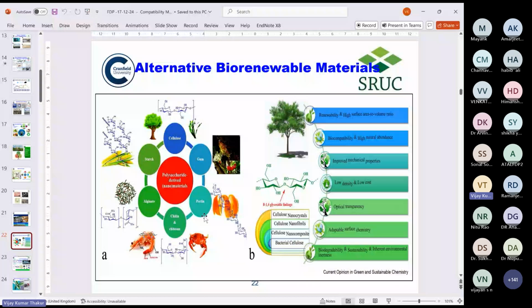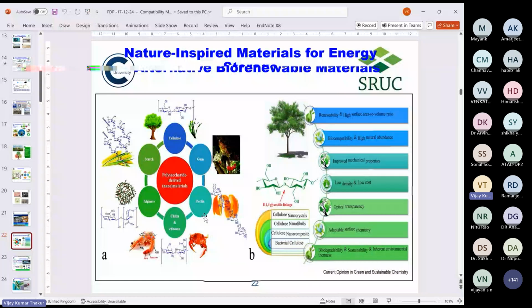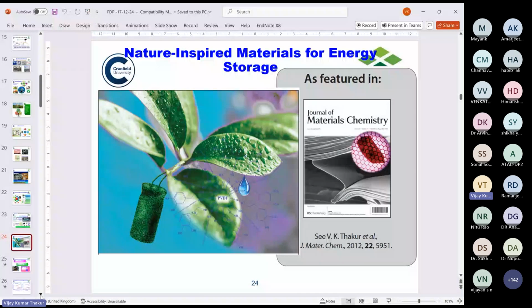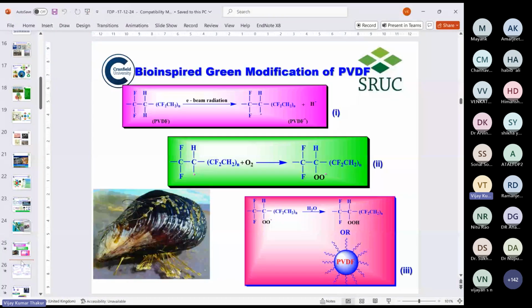And we have been mainly looking into different nature-inspired techniques, reducing the use of chemicals so that we can reduce the carbon footprint for these applications. PVDF is one of them; so far it is very difficult to engineer it with traditional chemicals. However, it is very sensitive to electron beam radiation, thanks to the sensitivity of its carbon-hydrogen bonds, so they start immediately degrading when we subject it. So we engineered PVDF polymer with an electron beam accelerator, optimizing different radiation doses and radiation times, because if we go beyond a particular radiation dose, say 2.5 megarad, then the backbone starts degrading, its molecular weight starts decreasing, and we don't get any enhancement in the properties.